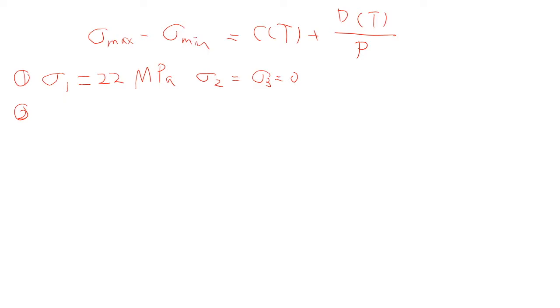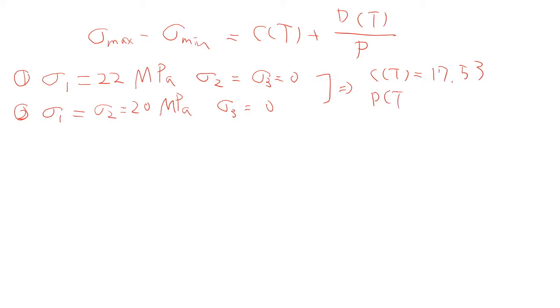biaxial tension, and we have sigma 1 equals sigma 2 equals 20 megapascal. This also means sigma 3 should be 0. In this case, we still have sigma maximum, which is 20 megapascal, and sigma minimum should be 0. So if we plug in these two equations, we can get the constants to be approximately 17.53, and the other one to be 32.79.